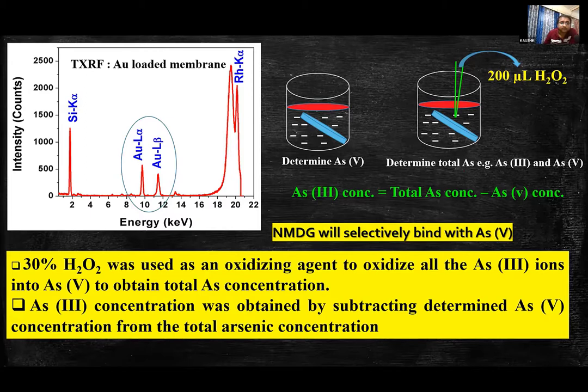So in the first step, I determined the arsenic 5 concentration, and in the second step, I determined the total arsenic concentration. And now the arsenic 3 concentration can be simply determined by subtracting the arsenic 5 concentration from the total arsenic concentration. So this is the strategy that I have used for the speciation of arsenic using this technique.